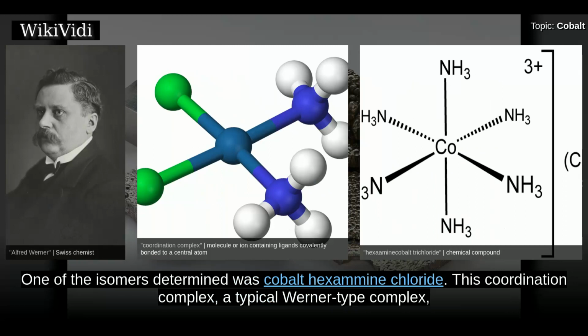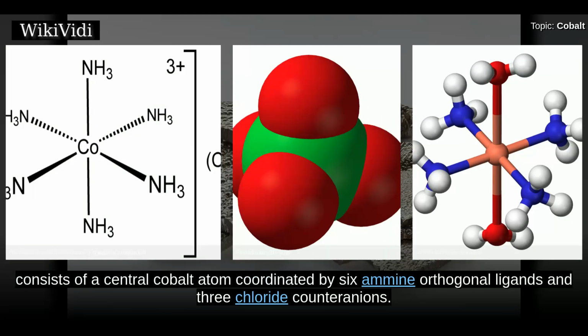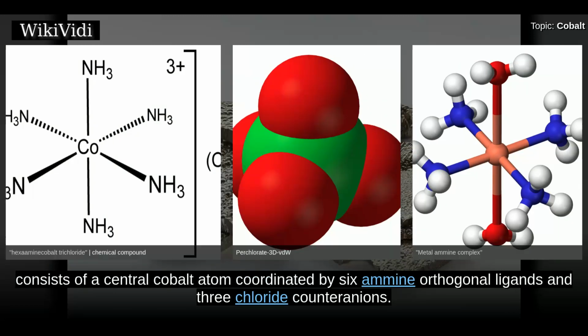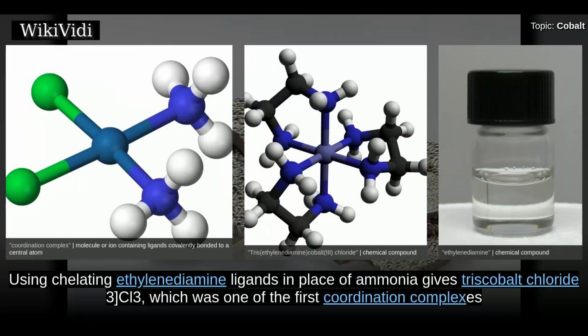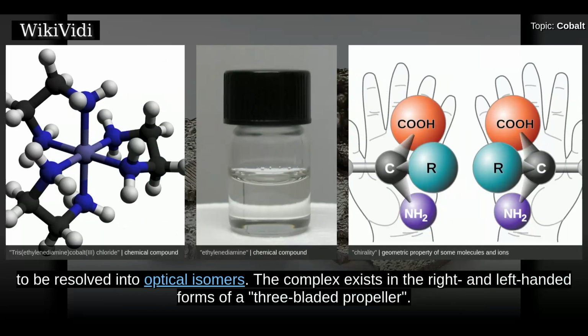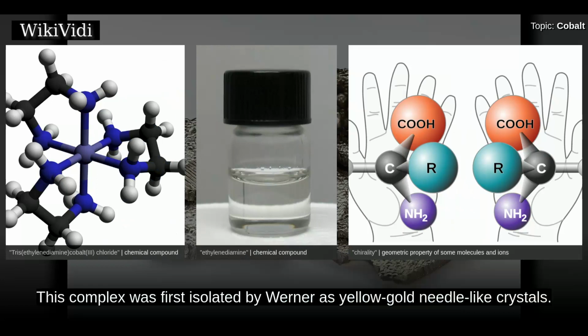One of the isomers determined was cobalt hexammine chloride. This coordination complex, a typical Werner-type complex, consists of a central cobalt atom coordinated by six ammine ligands and three chloride counteranions. Using chelating ethylenediamine ligands in place of ammonia gives tris(ethylenediamine)cobalt chloride, which was one of the first coordination complexes to be resolved into optical isomers. The complex exists in the right and left-handed forms of a three-bladed propeller. This complex was first isolated by Werner as yellow-gold needle-like crystals.